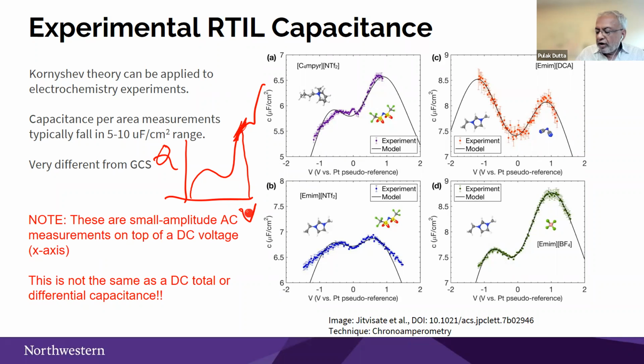That depends on V, as you see in these pictures, but it also depends on frequency, and that's not such a strong effect in ions in water, because the ions in water are relatively free to move. But these large, sluggish molecules have long dynamic effects, and therefore at different frequencies you're going to get different capacitance. Then the other definition of capacitance might be Q over V rather than dQ/dV, and that would be relevant for charge storage, which I was just talking about, and that's what we measure with X-ray reflectivity. So that's a different number.